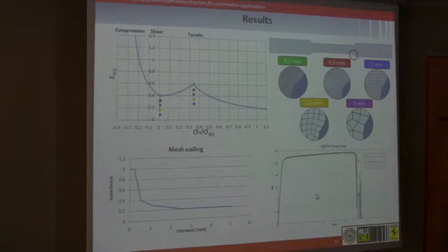Since the full vehicle model has a coarse mesh, it's necessary to tune the material card in order to get the same results for different mesh sizes. An empirical mesh scaling function is defined. This function describes the trend of a scale factor versus the mesh size.